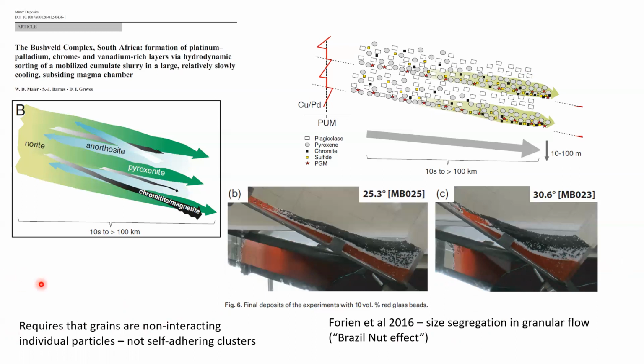We've seen that chromite grains in these kinds of rocks actually form quite big chains and clusters. And if you look at the size of them, they're several centimeters across. So if we accept the conclusion that I've been arguing for before, that these things are growing in place, then that kind of rules out the idea that you can make these things by just unmixing a loose crystal pack, because that assumption that the grains are non-interacting individual particles doesn't hold up.